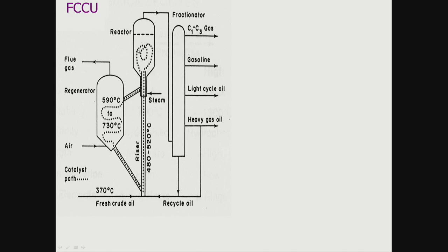Now it drops out, falls down the sides, and goes into the regenerator, where it's steam regenerated. Remember we said coking was a form of deactivation. So in that section there, you're using steam. You can see that you've got air and steam to help protect the catalyst at a high temperature. So your process in your riser is 480, and the temperature I've seen is up to 535 degrees C, but that's a good enough range. But your regenerator is operating 200 to 300 degrees hotter.